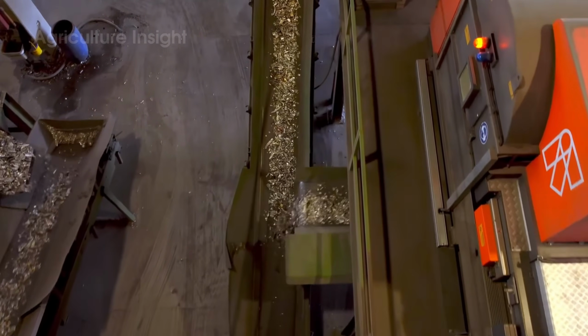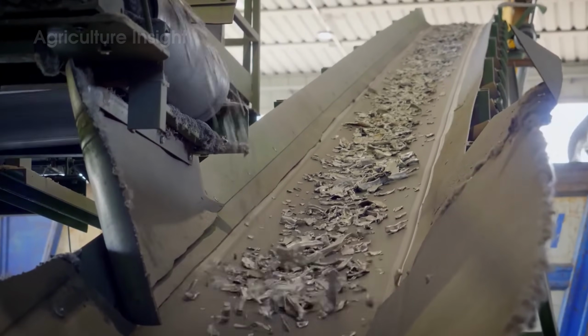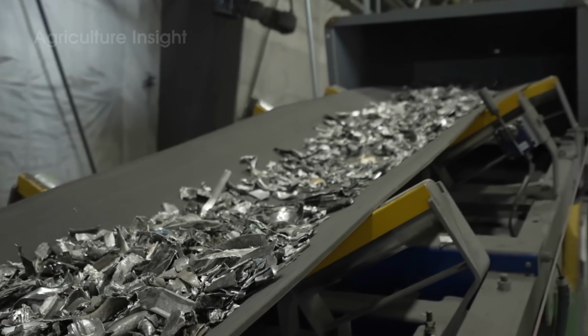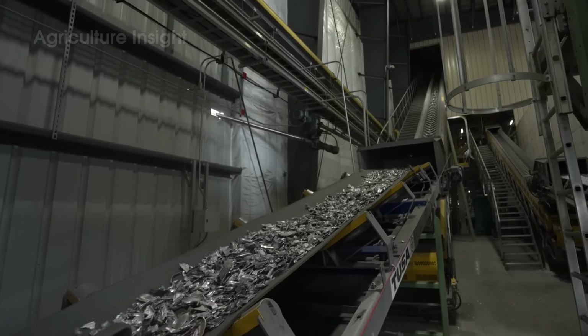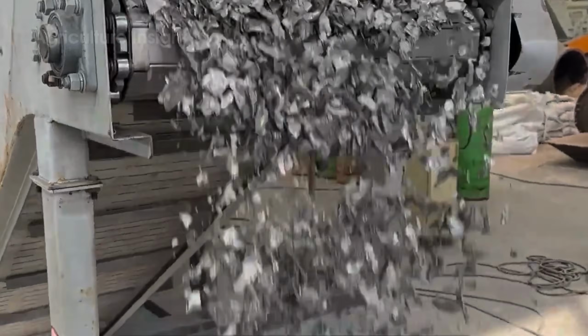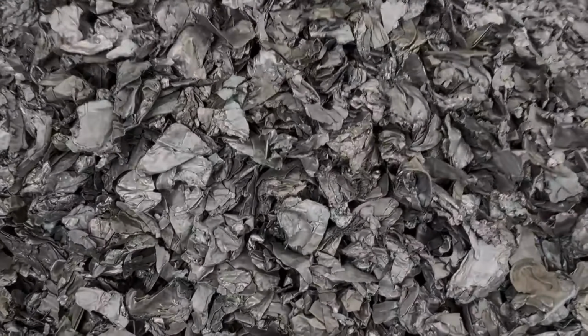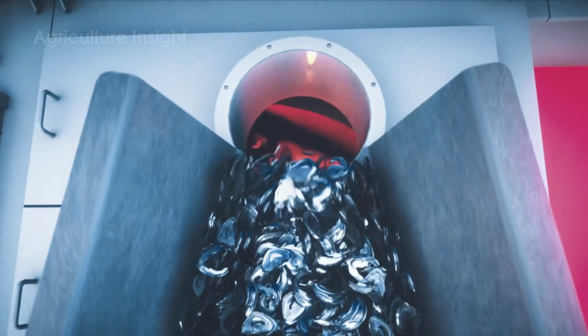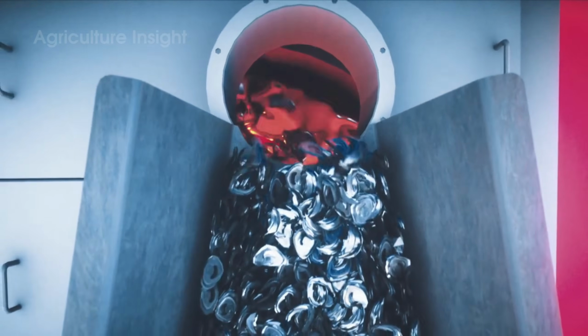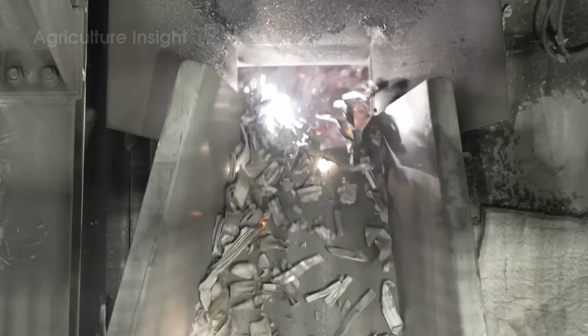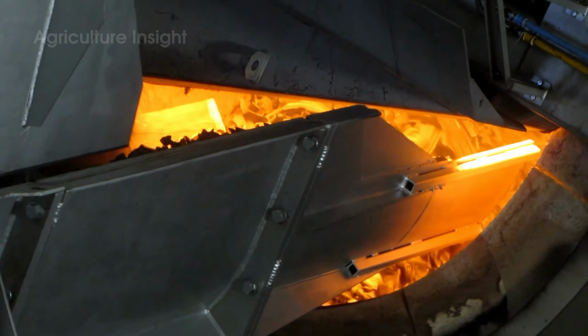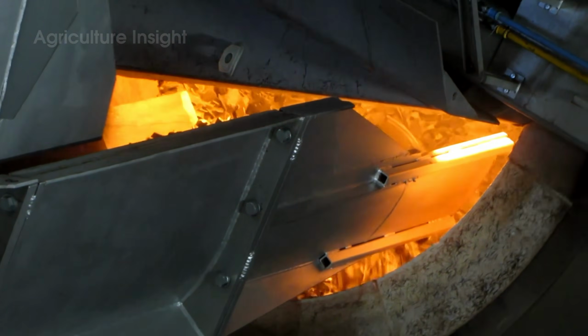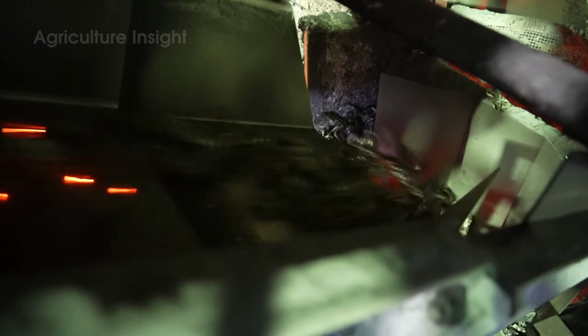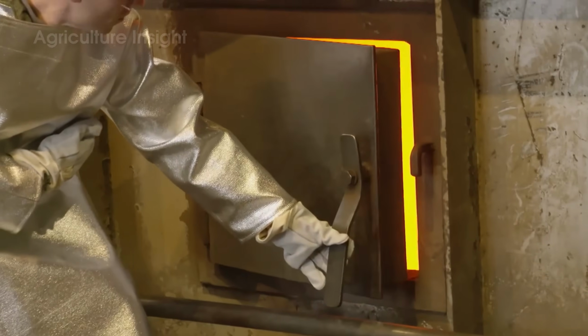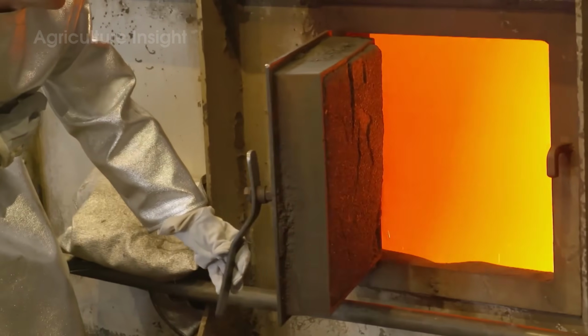This is a particularly critical step, as even a small amount of residual contamination can directly affect the quality of aluminum after melting. After impurities have been removed, the aluminum is transferred into industrial furnaces, where temperatures are raised to around 660 degrees Celsius, high enough to completely melt the metal. Under extreme heat, solid aluminum pieces begin to soften, deform, and gradually lose their original structure, merging into a glowing stream of liquid metal.